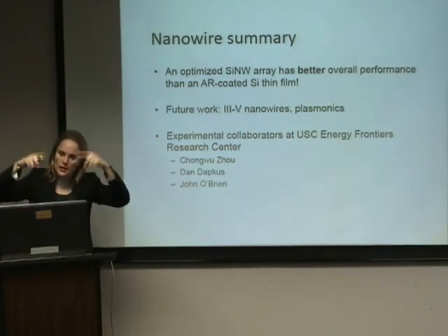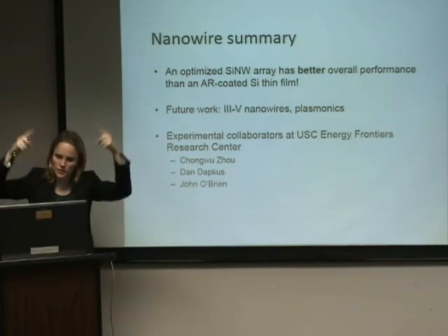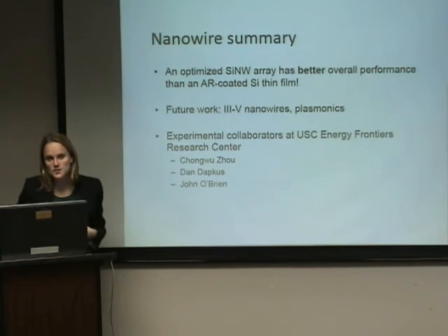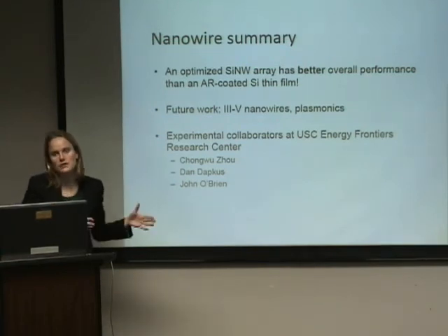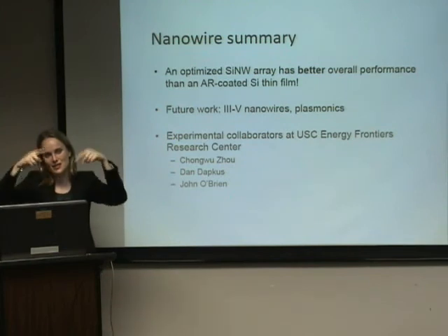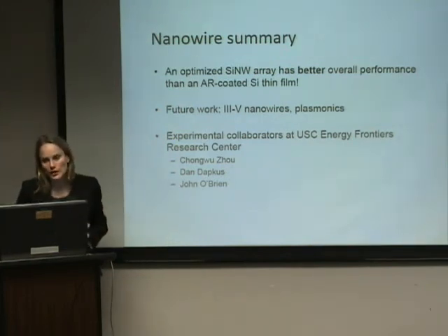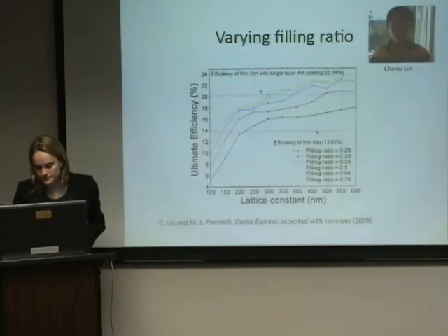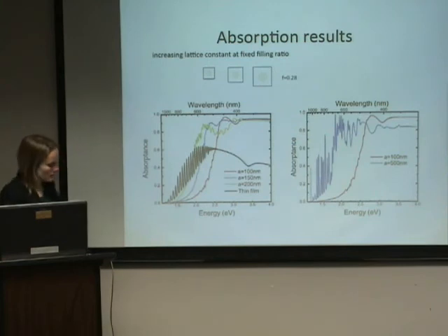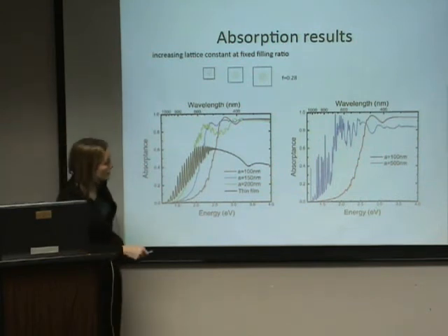With these ones, you can bounce off the bottom and back and forth, so you have an optical trapping effect within this cavity that helps increase absorption, but the amount of that increase will have some length dependence, which we are working on mapping out. So the peaks in your frequency function get closer to the simple function as the length of the fibers gets longer? Yes.